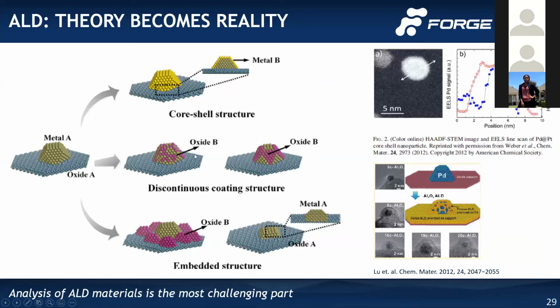These two examples at the bottom are from one of those review papers. You can have an oxide different from your support oxide, which can change your selectivity, or you can deposit around the material. This all depends on what you're depositing and what you're depositing onto - the combination goes to the lowest energy entropy state, depending on what conditions you take it to. Over here is an overcoat material, showing that overcoat on the palladium.